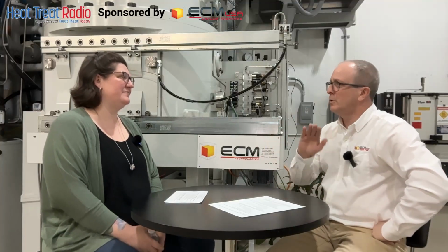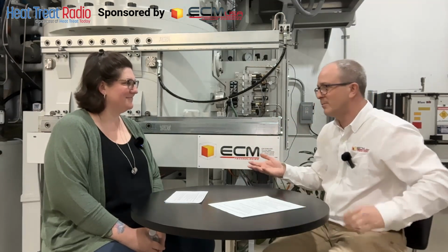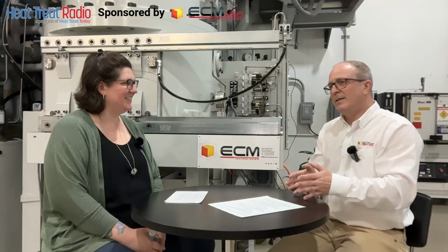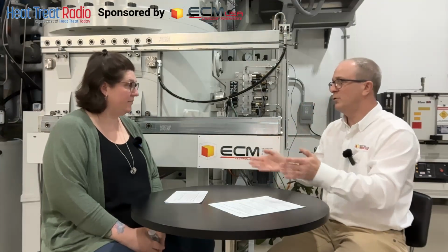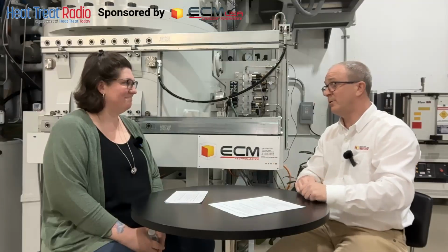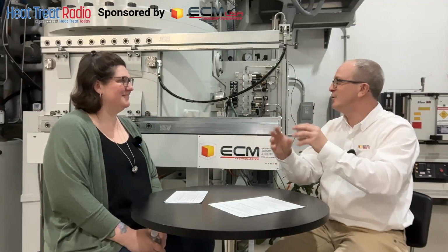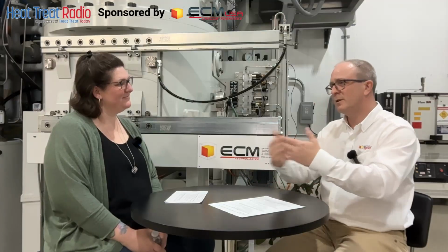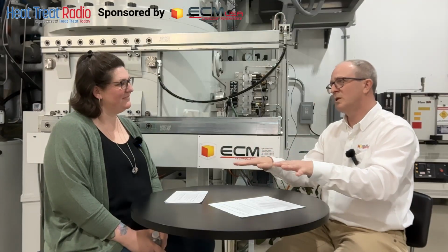It is. So you define your load, you define your heating time to be at temperature. And when you're sure you're at temperature, you start to carburize. I will speak about vacuum carburizing. First, we have a software for the carburizing boost and diffusion. So you put a few parameters and you have a generic recipe. Or if you like to go into detail, you can improve it. But directly the software will give you something and mostly it will work.